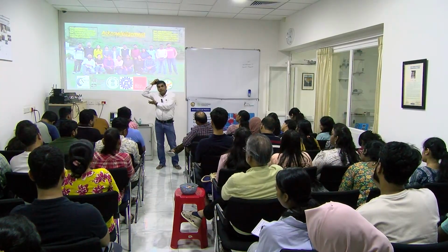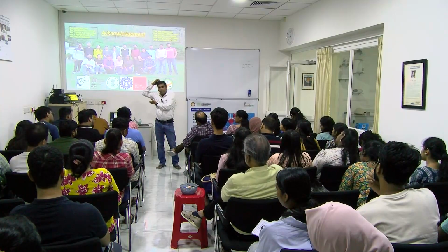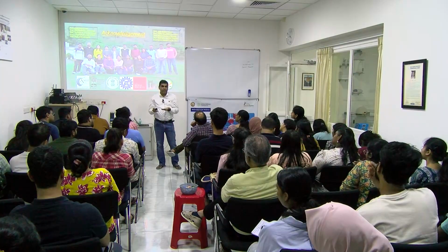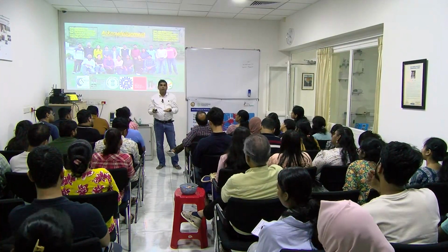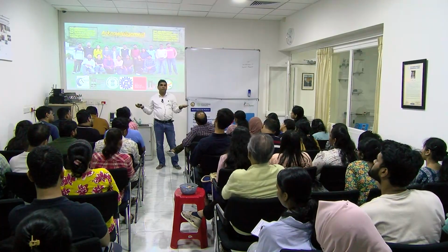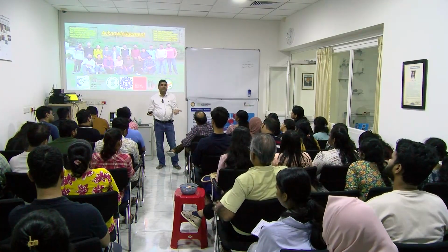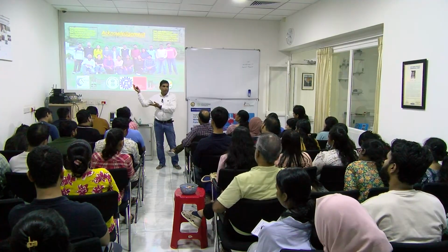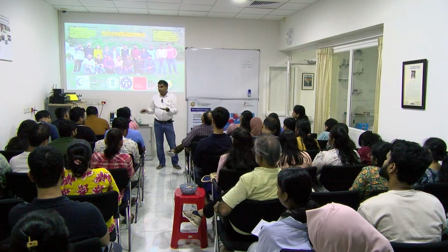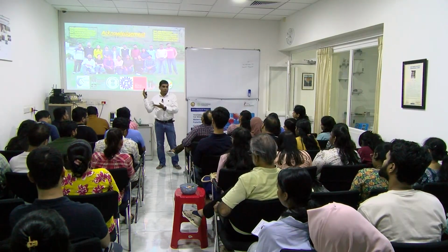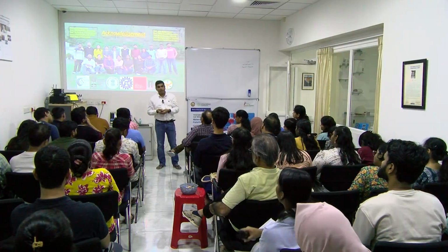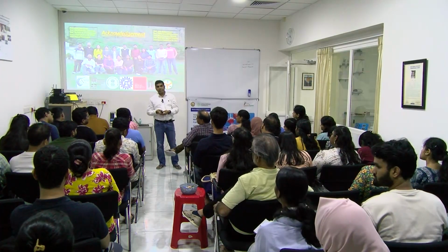As you see, the 25 nanoclusters, either gold or silver, have emission at around 700 nanometer, which is absolutely amazing in the red region, because everybody wants the red region. If you go to the molecules, your photostability as well as the quantum yield is drastically reduced. But in the case of these 25 nanoclusters, we have more than 20% quantum yield, which is absolutely amazing for any kind of imaging purpose. And you have seen the photon counts as well. It is around 70,000, which is extremely high for any kind of single molecule or imaging technique.